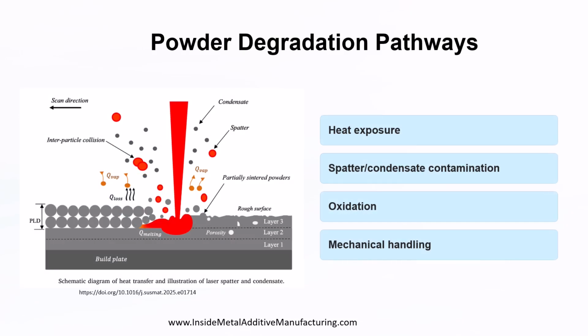Now that we understand the stakes, let's look at what actually happens to the powder inside the machine. When the laser hits the powder bed, particles near the melt pool are violently expelled. This creates spatter. Particles that are much larger than the original powder, often irregular and usually coated in oxide. Many of these spatters fall right back into the powder bed, slowly contaminating the feedstock. Meanwhile, the intense heat also generates metallic vapor, which cools and resolidifies as ultrafine condensate. These condensate particles, rich in oxides, settle across the bed and dramatically alter how the powder flows, how it absorbs laser energy, and even its thermal conductivity.